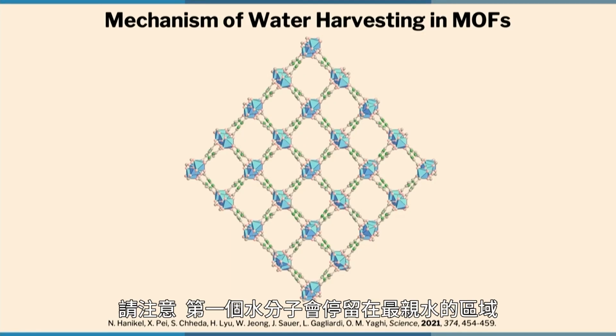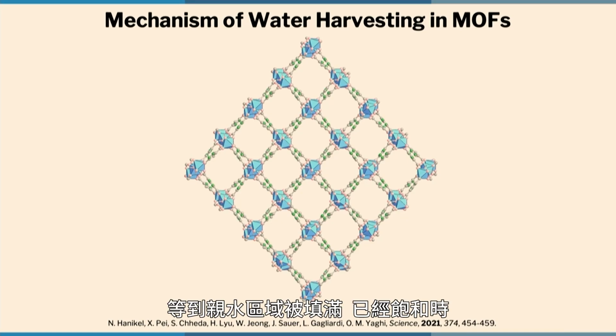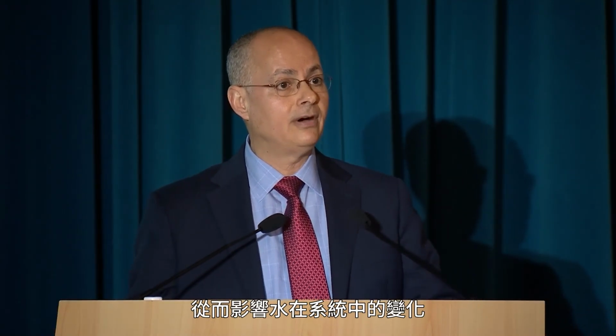We're going to extract one of these pores out and slice it and show you where each water molecule resides. Okay, and notice that the very first water molecules sit in the most hydrophilic region. And when the hydrophilic region is filled, is saturated, there is next to it a hydrophobic region. So really the interior of the MOF is a grid of hydrophobic, hydrophilic, hydrophobic, hydrophilic. When the hydrophilic pockets get filled, they bridge over the hydrophobic regions. And so this pull-push of the hydrophilic and the hydrophobic allows you to control the temperature at which water could be evolved from the system.